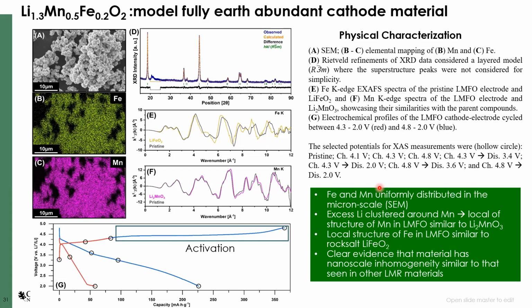The last example that I'm going to talk about is this lithium and manganese-rich material, which is a cathode material made exclusively with earth-abundant materials. Now, if you look at this material on the average length scale with X-ray diffraction, what we find is that it forms a layered compound.